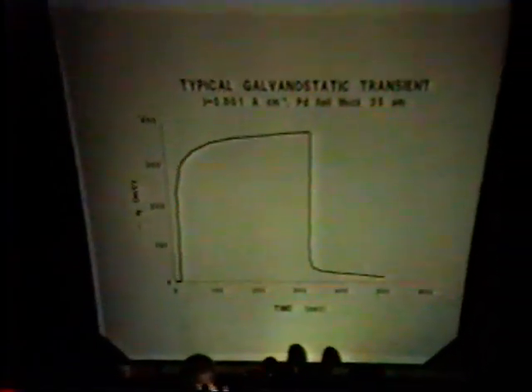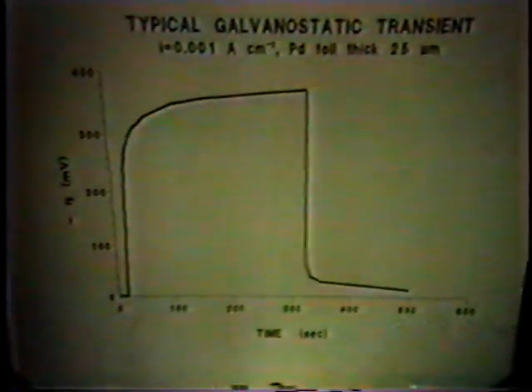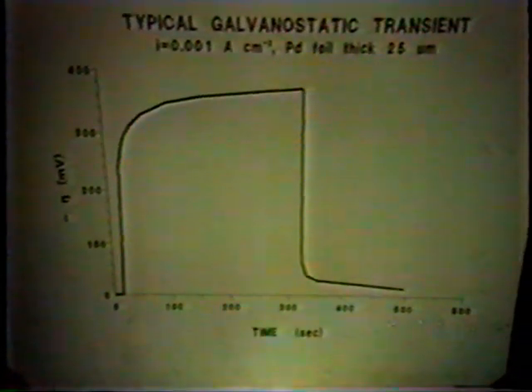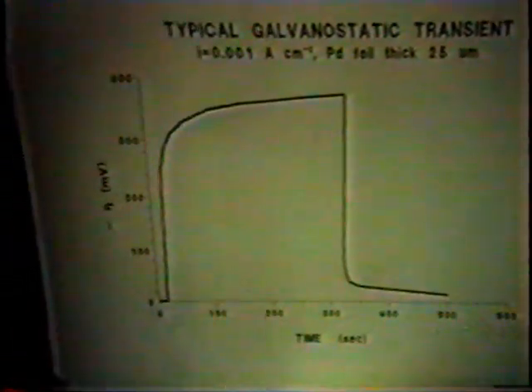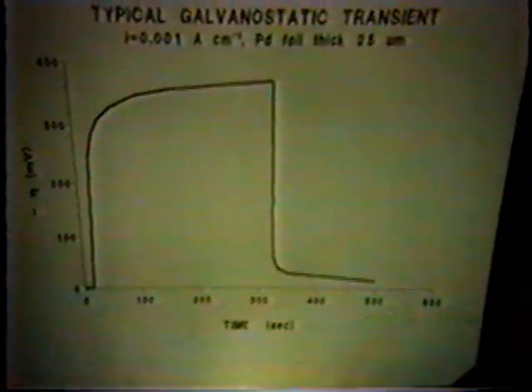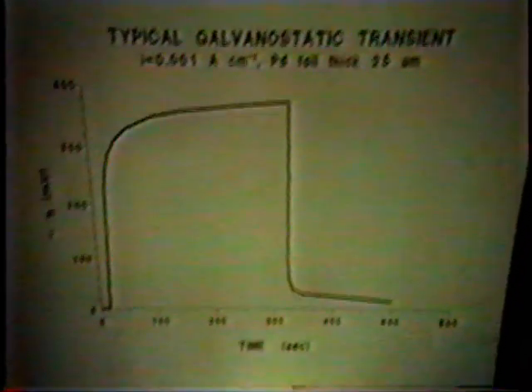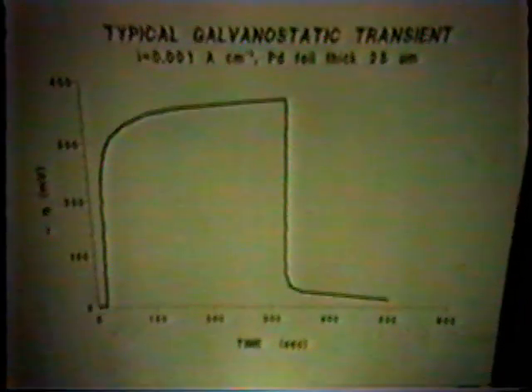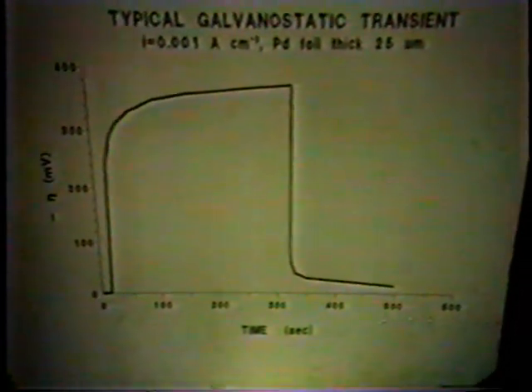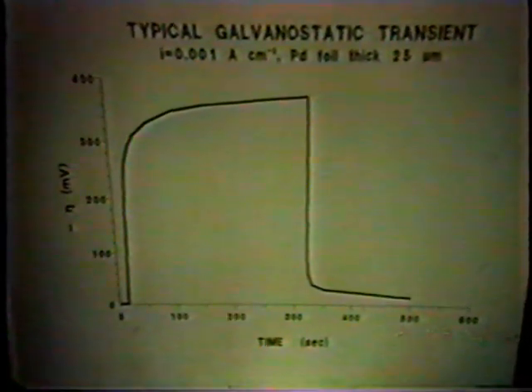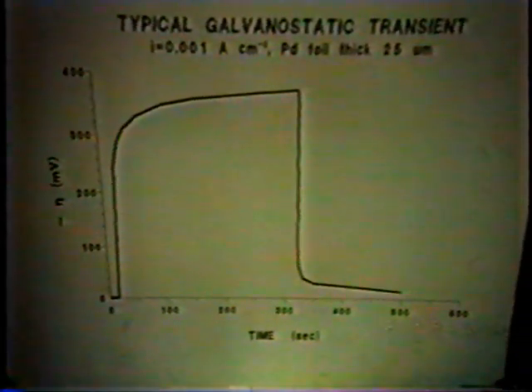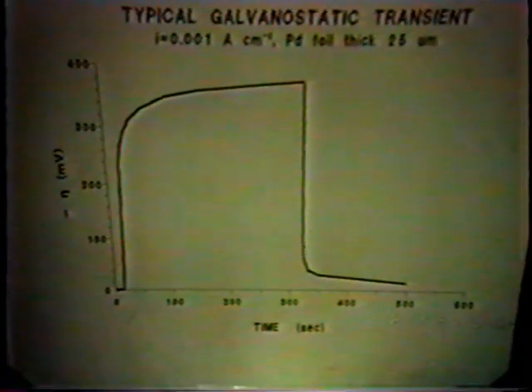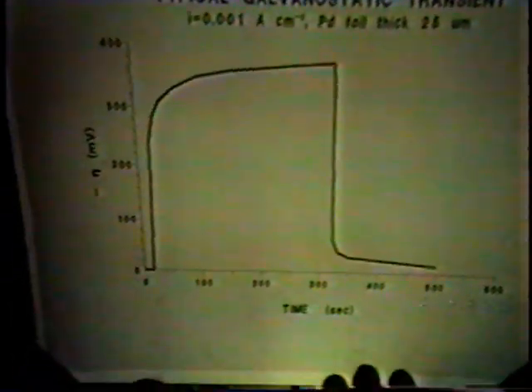Well, now let me present very briefly the other work we've done so far on mechanism. This is Dinescu's work at Texas A&M. There's a typical, what we call galvanostatic or constant current transient. We put onto the palladium, and this palladium, I must be very clear with you, is young palladium, not yet the palladium that corresponds to, say, 2 months electrolysis. It's a much more difficult thing to do. This is what you might call normal palladium, where you prepare it, you clean it, you put it in a solution, and make the measurements over an hour or 2. That's the kind of palladium this is. And it has its own problems, as we shall see.